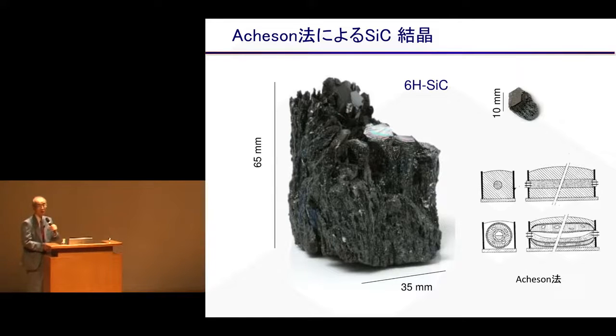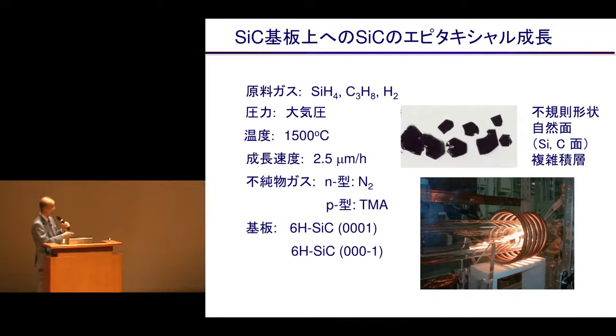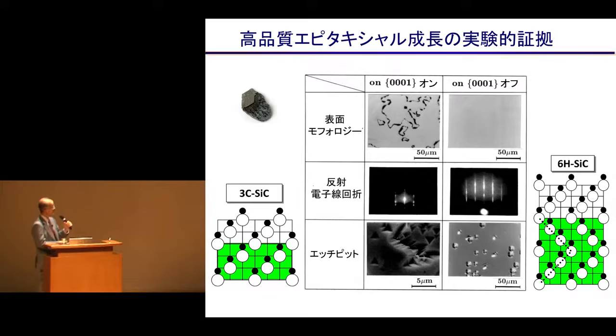And so for the silicon carbide substrate, we had no substrate available in the market at that point. For the abrasive or for the fire brick, there was an industrial material, a single crystal shown here. This part was cut off by hammer, the reverse side was polished, and silicon carbide was to be grown on this surface. It's not silicon, so we could elevate the temperature. We had a reactor that we made for this research. You see the natural surface here, and we put an angle here and attach it to the surface where it's polished. Then, if we observe the surface morphology, it becomes very smooth and shiny.